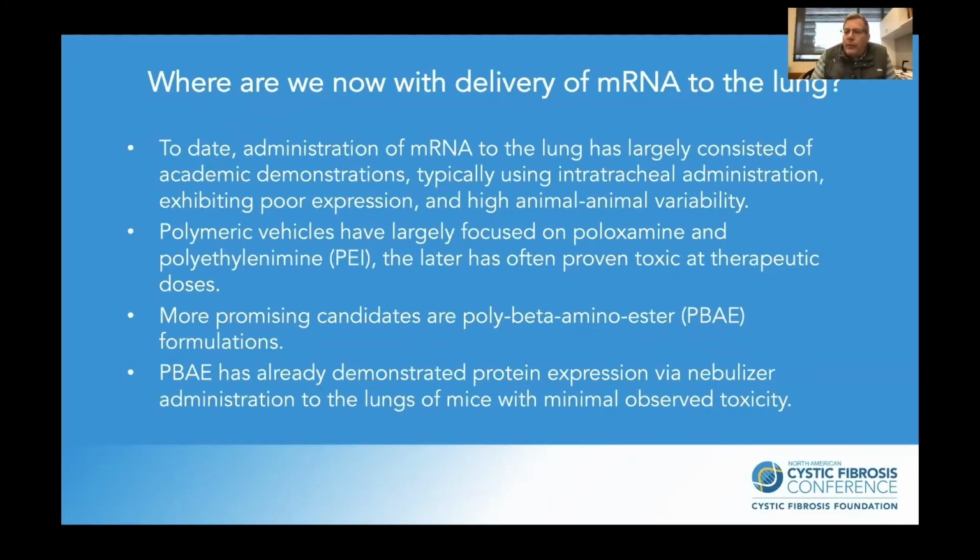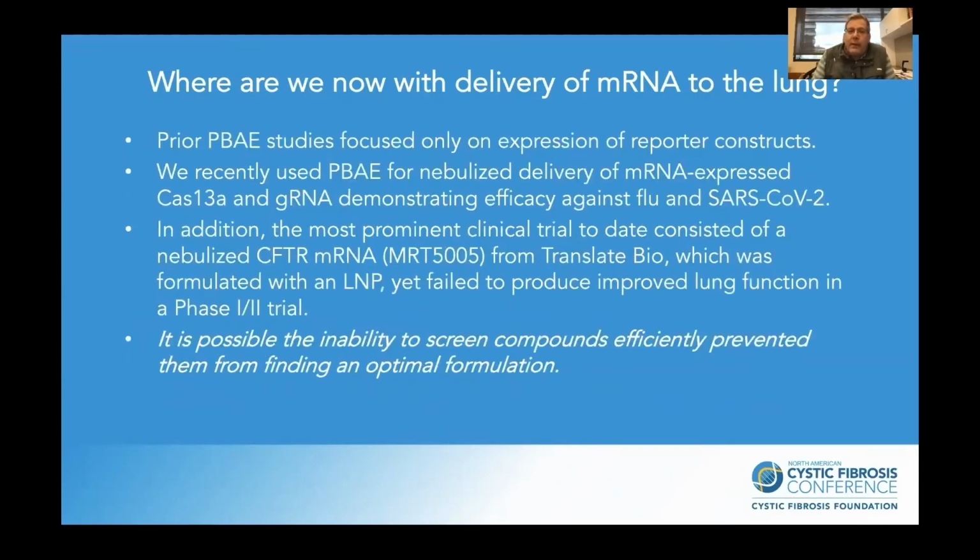There have been a number of polymeric vehicles that have been published. Many are focused on PEI, and one of the issues with PEI is that it's quite clear that the toxicity of PEI, at least at therapeutic doses, could be an issue regarding their translation into the clinic. What's probably a bit more promising is PBAE-based formulations, so poly beta amino ester-based formulations. These have been successfully used by the Anderson lab to demonstrate protein expression via nebulization in mice with minimal toxicity.